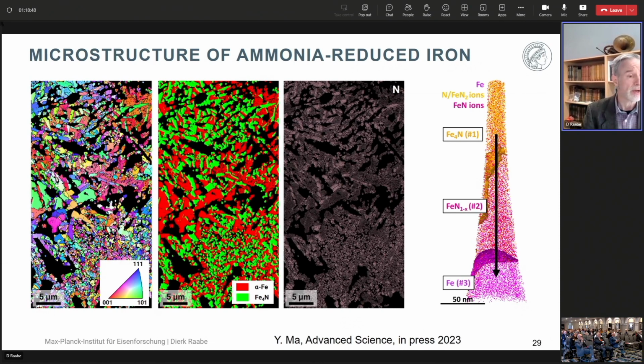Then you produce a fraction iron nitride, as you see here, and alpha iron, and you produce, so to say, an iron nitride sponge. You charge that into an electric arc furnace, you melt it, and due to the vapor pressure, the nitrogen goes out and you have pure iron. That means you can make pure iron with green ammonia also. And we work, as I said, on other vectors too.